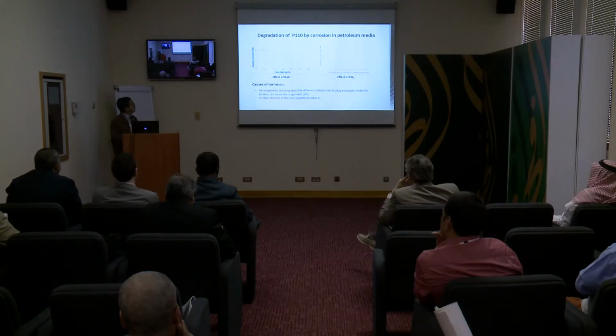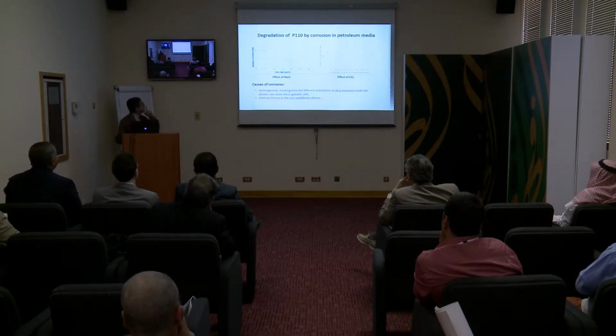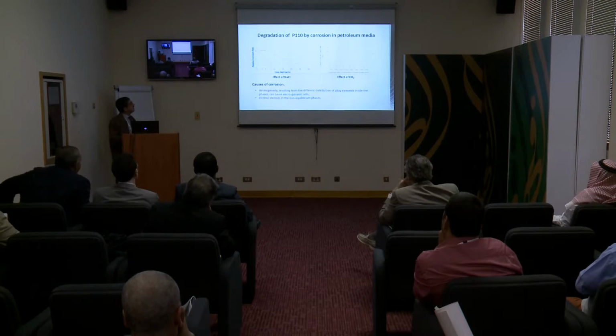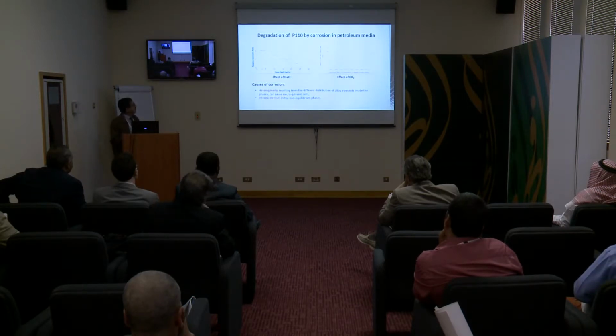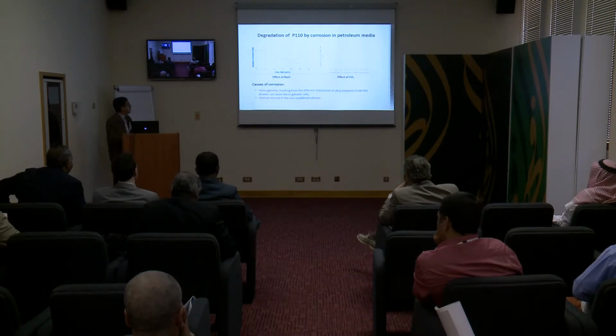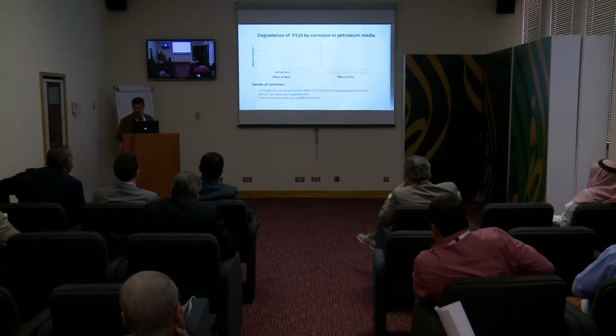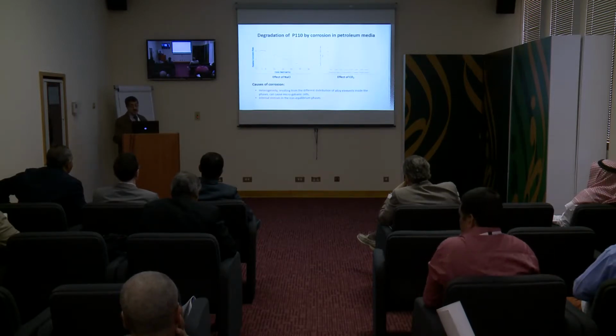But in fact, we can see the curve at the right. Well, when you are in effective industrial conditions in petroleum media, you have the presence of sodium chloride and carbon dioxide, which have a detrimental effect on the steel when they are in specific concentrations. And especially the corrosion which is caused because of the heterogeneity resulting from the different distribution of alloy elements and the internal stresses because of the formation of some non-equilibrium phases.